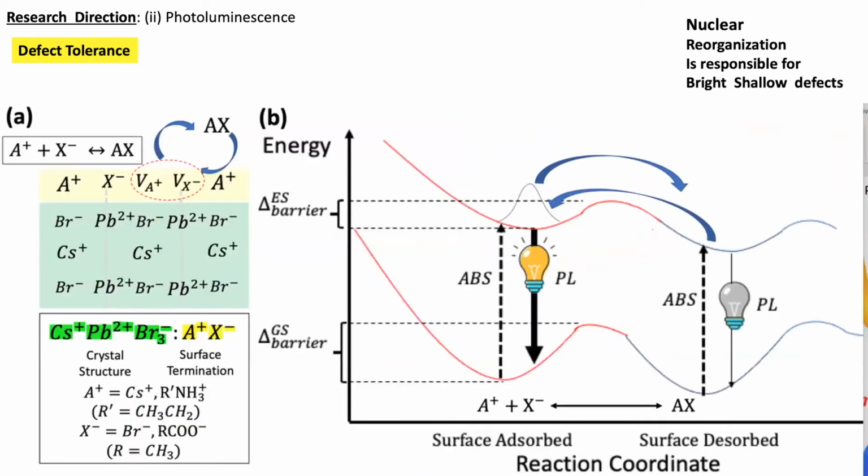The surface of quantum dots is passivated by dual types of ligands, anions and cations, which are a little longer than native anions and cations in this ionic crystal. There is a chance that by photoexcitation there is a photodesorption of ligands. If they desorb, then since they are anions and cations, they can recombine back into a chemically neutral molecule, leaving part of the surface of this nanostructure unsaturated, not covered by protective ligands.